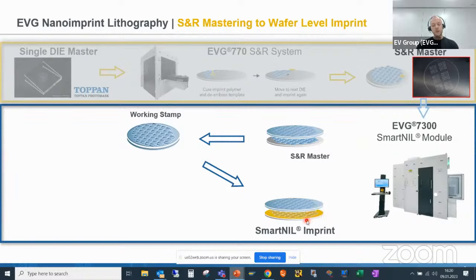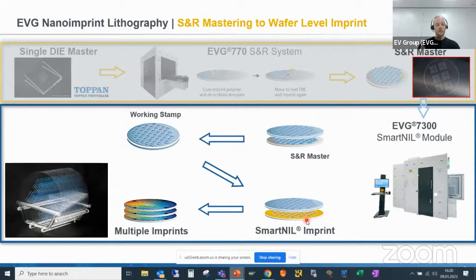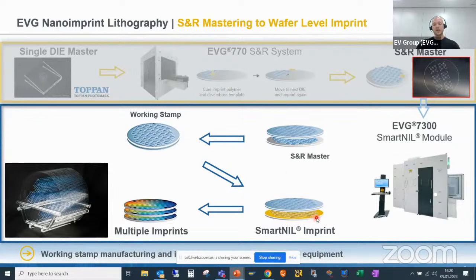After curing the polymer, we detach the working stamp, and then we can create multiple imprints with this stamp. Depending on the structures, you can create, for example, one batch of wafers like here, so 25 imprints or even more. The main benefit is that the working stamp manufacturing and the imprinting is performed in the same equipment. So we do not have to exchange any hardware, except, for example, the imprint chucks when you want to imprint on different sizes of wafers. But the working stamp is mounted inside the tool, and we do not unload it or cause any risk of contamination or damage of the stamp.